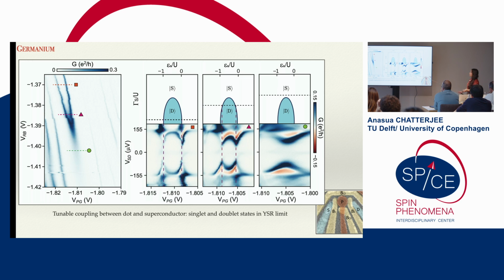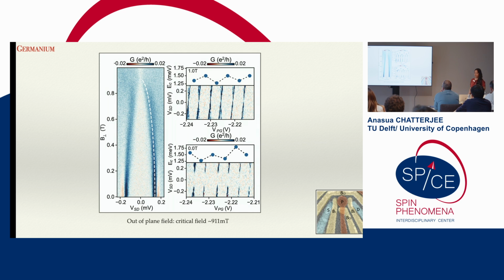And so what's nice is that you can indeed get to the type of states that people use for instance, maybe doing an Andreev spin qubit. You can look at the charging energies versus the gap and things like that, but it's nice that you can have these controllable bound states, for instance. Even in this proximatized system, you still see an out-of-plane critical field of about 900 millitesla, which is pretty good. That's pretty, I would say, encouraging to be able to do some experiments in this kind of intermediate range.